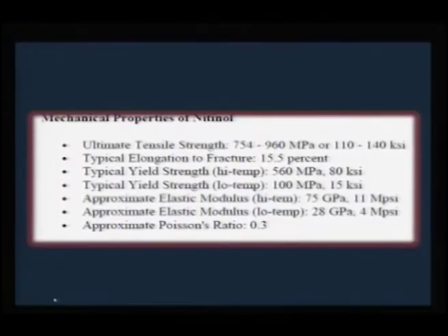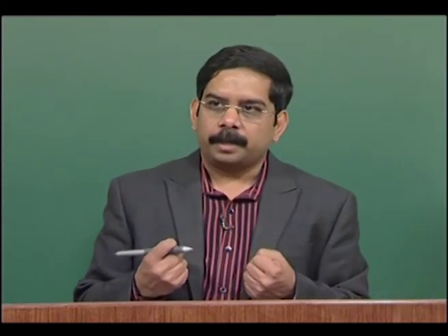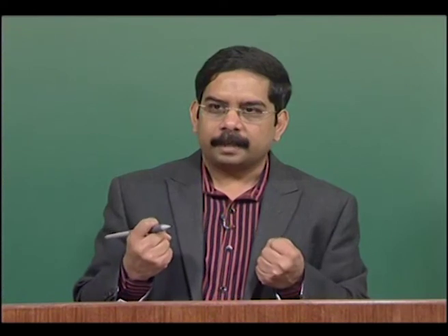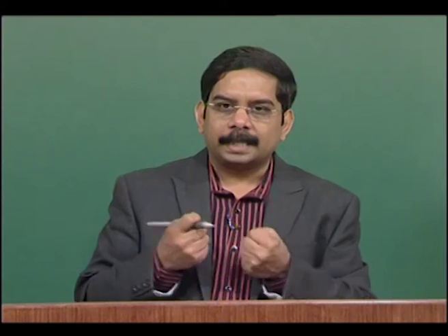Mechanical properties are also equally important when we are considering applications. Therefore, some of the values that we can have in mind: typical yield strength is 560 megapascal and 100 megapascal at low temperature. Then tensile strength ranges from 754 to 960 megapascal, because when you are trying to use pressure to induce shape, then you need to know what tensile strength it can take. Otherwise, if you exceed the tensile strength, then it will break, it will get totally deformed.